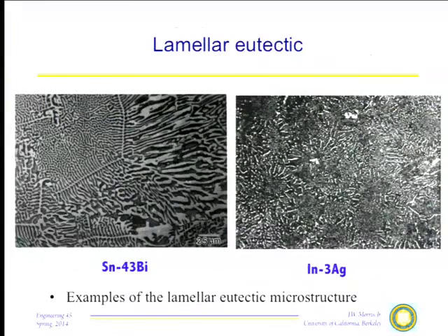Let me just give you some quick examples. This is the eutectic. Here are examples of lamellar eutectic. This is a tin bismuth eutectic. You see it's not a perfect arrangement, but an essential arrangement of parallel plates, with some irregularity. Incidentally, within these colonies, you tend to have two crystals. The interconnectivity is such that the tin, the light phase I'm pretty sure here, is all the same crystal, and the bismuth is all the same crystal. They're just intergrown to form these eutectics.